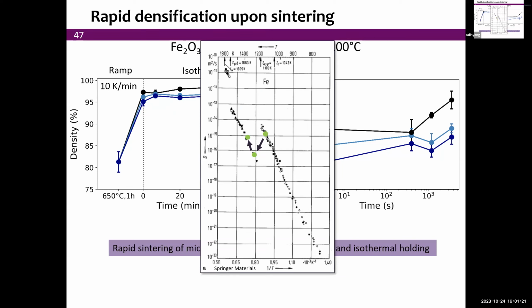This is the diffusion coefficient as a function of 1 over T, so an Arrhenius plot, and normally it's just a straight line. But we have a phase transformation. We go from BCC iron at low temperature, which is kind of going up like this. This is 1 over T. There's a phase transformation from BCC to FCC. BCC is not close packed, so it's rapid diffusion. FCC is close packed. So in fact, the diffusion coefficient D drops as you go from 800 to 900, and